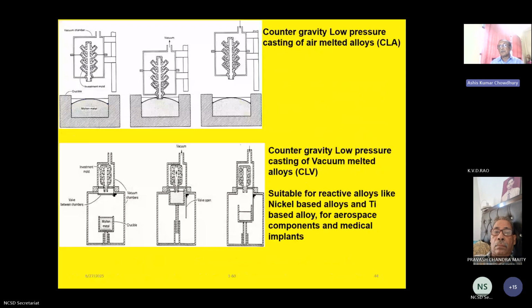This is the diagram generally available in the handbook. Counter gravity low pressure, here it is showing the first stage, inverted condition, just reverse inverted condition of the ceramic mold. The red hot ceramic mold is placed inside a steel box. And from here, it will come down to the liquid metal. This sprue will go inside, just below the first layer, so that inclusion does not go inside. Liquid will be drawn from the central portion of the melt. So always you will get very clean liquid.